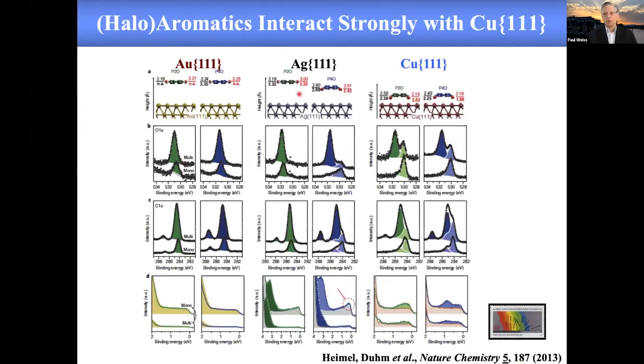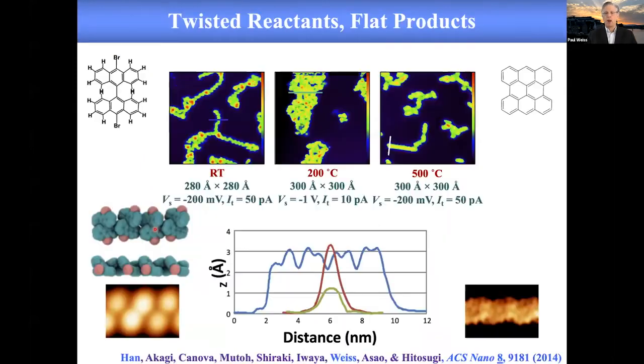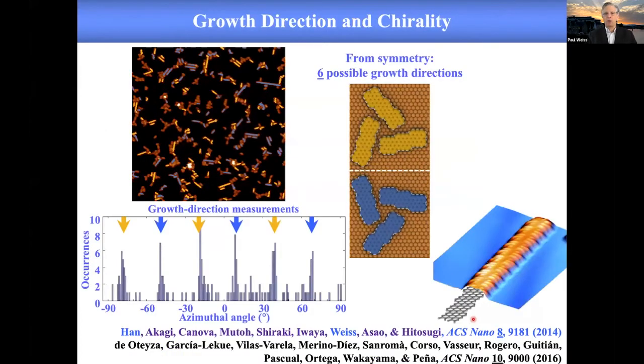Okay. And so he was able to see these molecules before reaction as intermediates, and then upon raising the temperature and cooling again, the graphene nanoribbon that was formed. And indeed, he formed chiral graphene nanoribbons. According to the growth direction, they'd be left or right-handed. We don't have a color STM. He just color-coded these according to the growth direction, showing that they go left, right, left, right, left, right, like this.